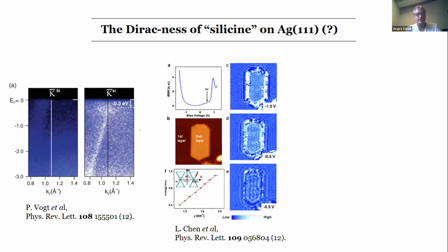If we now address the electronic structure of this system, in the seminal paper, as I said before, they claimed that they had seen a Dirac cone. This was the system without silicene. This was when they adsorbed silicene, and they claimed that they were seeing this Dirac cone here, which would be slightly doped.